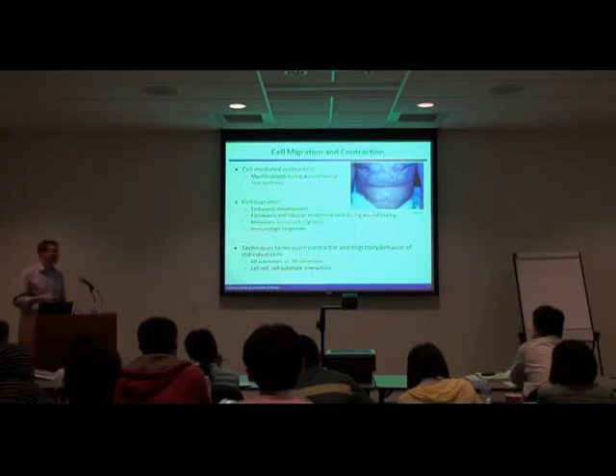What this biomaterial had been designed to do is actually prevent cell-mediated contraction. When you looked at the healing a year later, the area treated with a conventional skin autograft had a lot of associated contraction and scar formation, and the area treated by the biomaterial designed specifically to prevent cell contraction actually led to regeneration of a fairly complete skin. There were no sweat glands, no hair follicles, but functionally it behaved like skin, mechanically it was like skin, and aesthetically it was like skin. So that's one area that we're very much interested in.